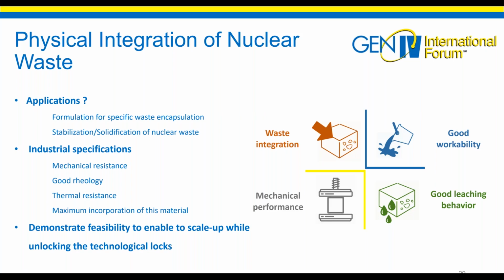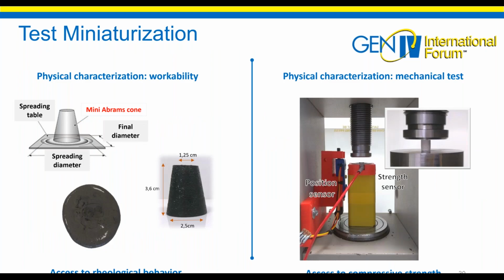technological lock. I'm going to tell you about a specific work I had to do in the laboratory to allow me to work on a small scale, which saves raw material during the formulation phase. Civil engineering tests are carried out on large sample quantities and volumes. However, for reasons of raw material saving, the miniaturization of the tests was one of the key points of my thesis. In the fresh test stage, this has gone through the miniaturization of a mini Abrams cone by a factor of 4. This allows me to quickly evaluate the rheology of my small-scale formulation.